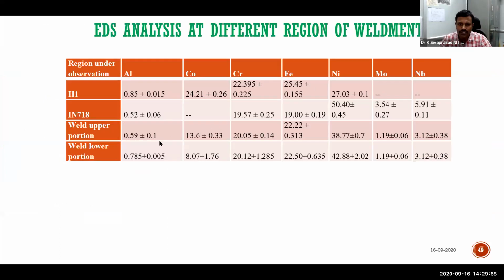Elemental distribution is almost uniform. We can say that the uniformity associated with the system is comparable to that of the high entropy alloys. That is, say, aluminum 0.8, in the sense, almost closely maintained. Then cobalt, compared to the weld and this one in the high entropy alloy, cobalt is depleted because diffusion will take place on the high entropy alloy side, Inconel side. That's a very common thing because of cobalt's affinity towards nickel. Then chromium.